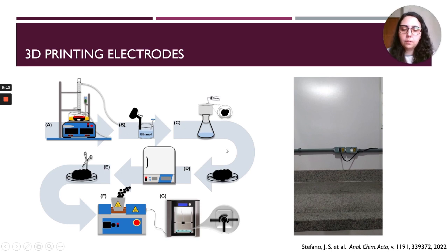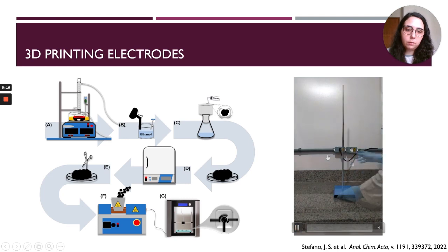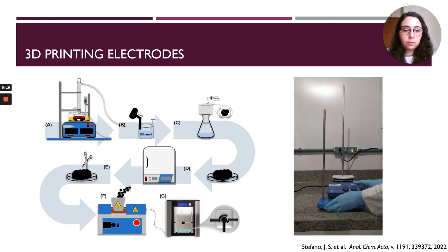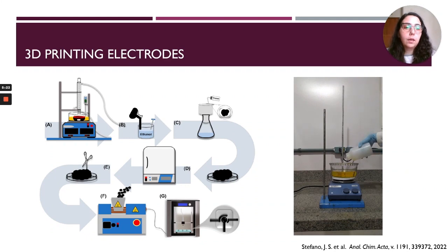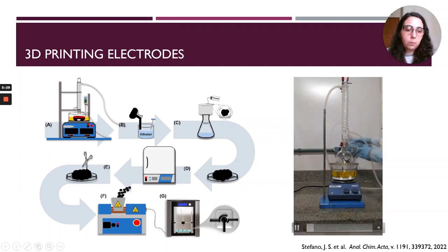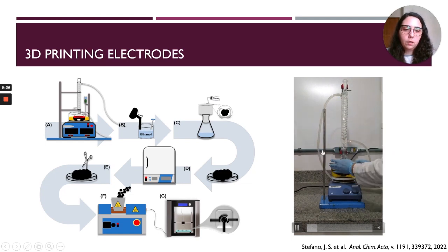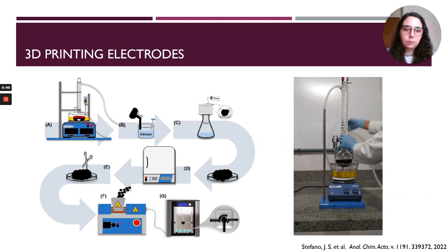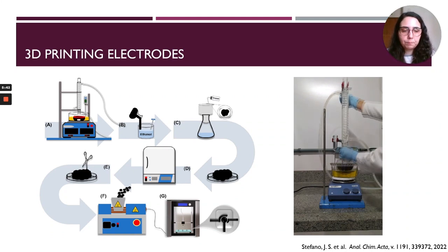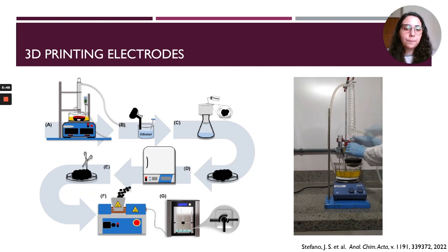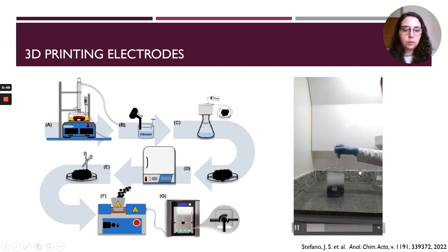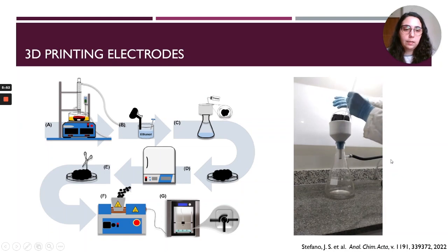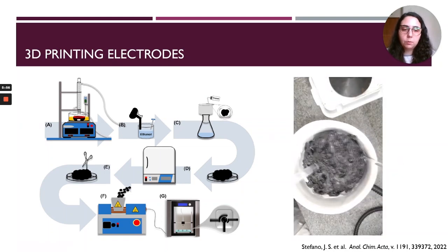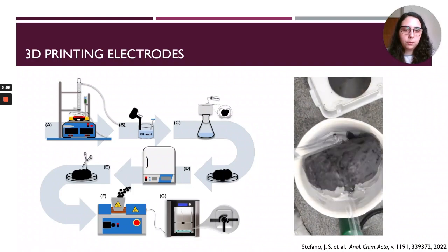Here on the left side of the slide, you can see a summary of the process, and here on the right side, you can see a video. So first of all, what we do is we mix the polymer and the graphite in a reflux bath with oil. So we add the graphite, and we use a temperature of around 70 degrees Celsius. Then the polymer is added, and once everything is mixed well together, we add everything to ethanol, and you can see that it gets recrystallized. Then everything is washed with ethanol using a filter and a funnel.